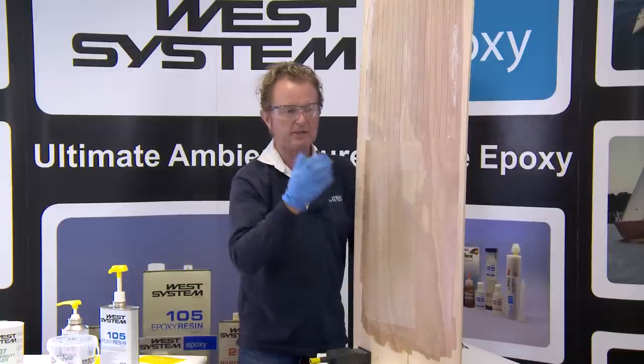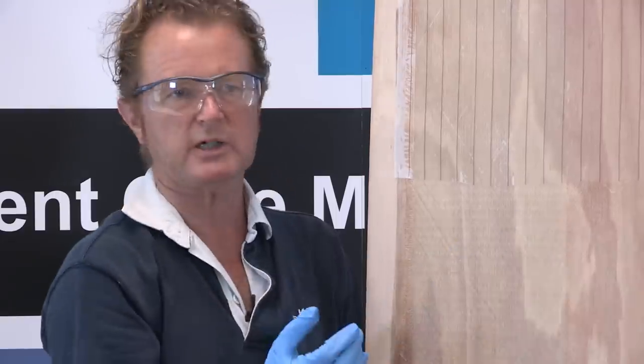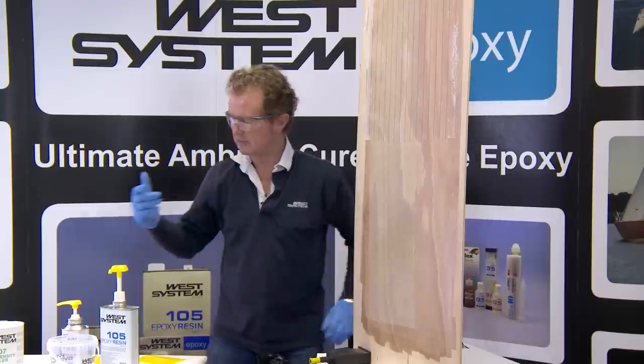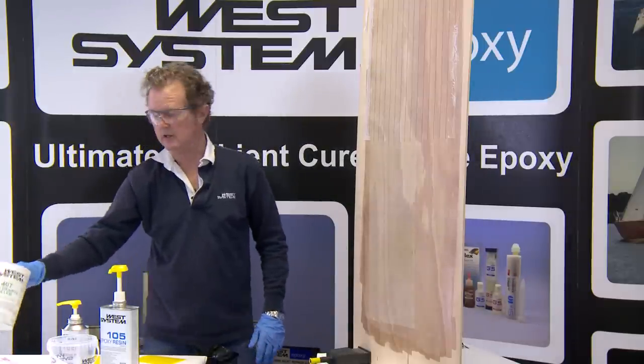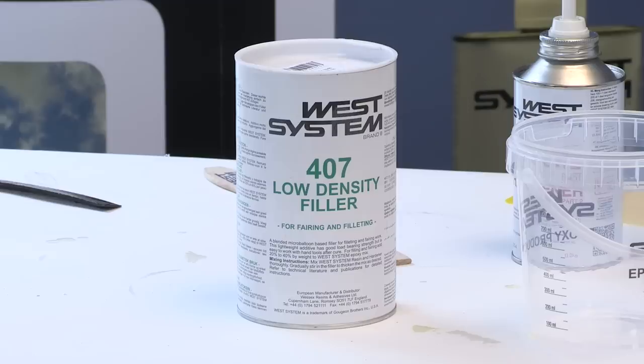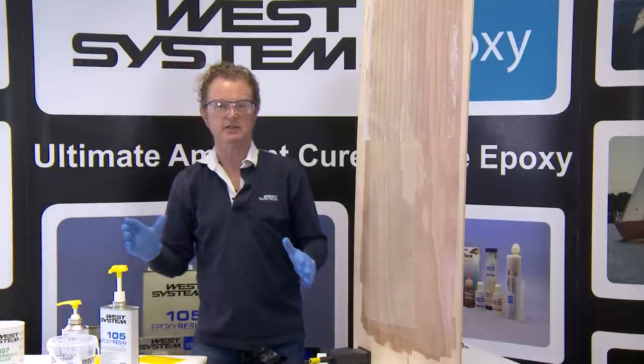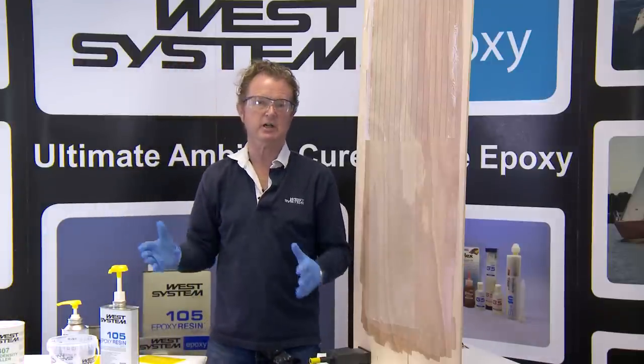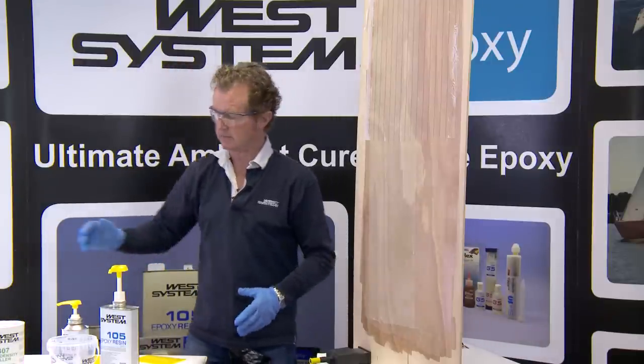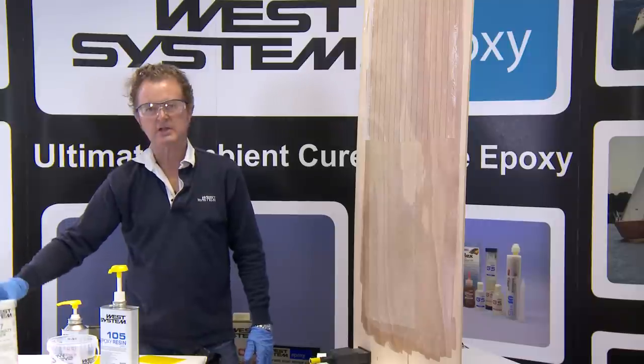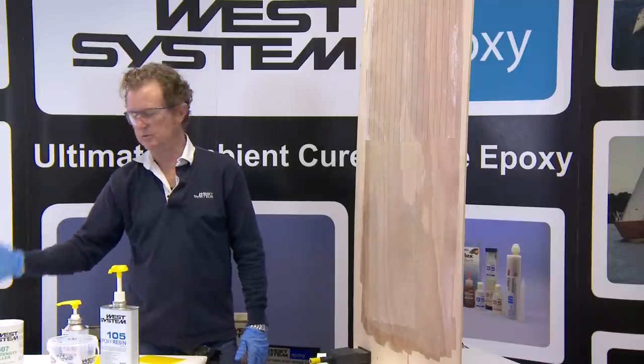The idea behind that is that by filling the weave, when we come to sand, we don't cut through any of these really, really strong glass fibres. Now, the ideal filler to do that, or one of the ideal fillers, is the 407 low density filler. There are three low density fillers in the West System product range: the 407, the 409, and the 410.